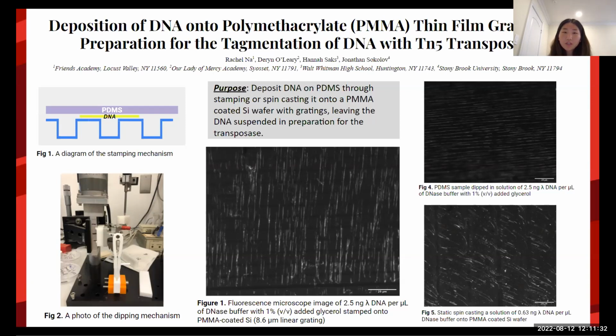We dipped a PDMS sample into a solution with a concentration of 2.5 nanograms lambda DNA per microliter of DNase buffer with 1% volume over volume added glycerol, as shown by figure 4, and stamped the PDMS across an 8.6 micron linear grating for 15 seconds and no wait. We saw consistent amounts of bridging across the wafer.